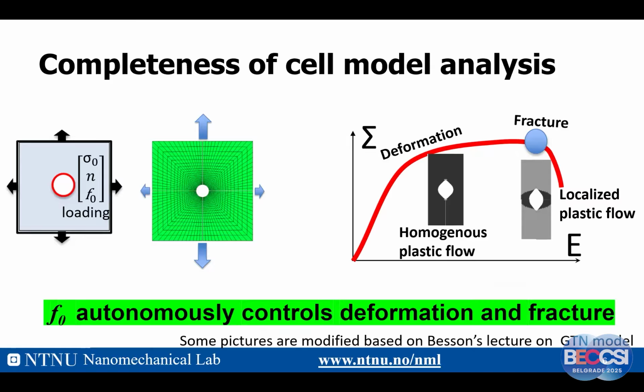And then we apply a load to this cell model. Then we will have output. On the right-hand side is the output. We will have deformation and fracture. That means this cell model can, in fact, we can use the word autonomously, control deformation and fracture. Deformation is a homogeneous plastic flow, and fracture is a localized plastic flow. So that means the cell model can reveal both the deformation and the fracture. That's important. And that means it's complete. The cell model is complete. It can reveal both deformation and fracture.